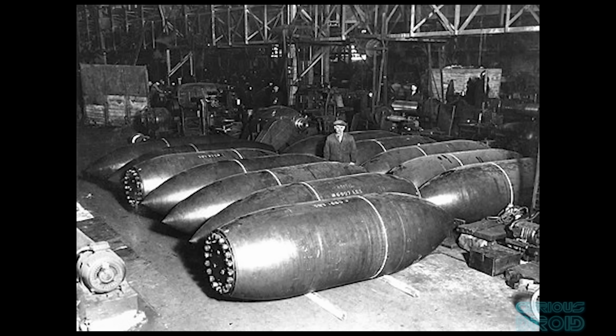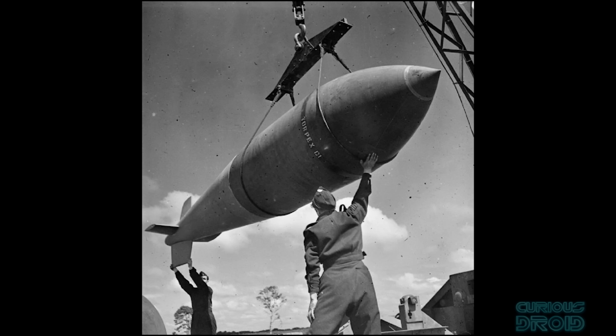the bombs were made from a steel alloy of chrome molybdenum, and just over half the weight came from the case alone. Using their streamlined design, mass and speed when they were dropped from up to 22,000 feet, the 10-ton Grand Slam could puncture up to 6 metres of reinforced concrete and then explode inside.